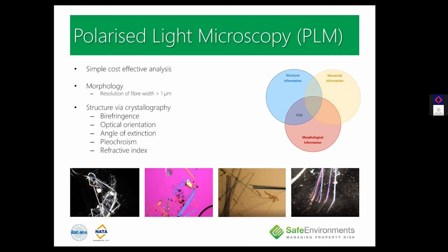Polarised light microscopy alone cannot unequivocally differentiate between tremolite, actinolite, and amosite because of the overlapping refractive indices. It's claimed by some that this issue can be resolved through assessing the extinction angle. This is wrong, as one simply needs to refer to Table 4 of the International Standard ISO 22262-1, where the HSC reference materials all have parallel extinction. This is where elemental analysis is required to resolve these varieties.